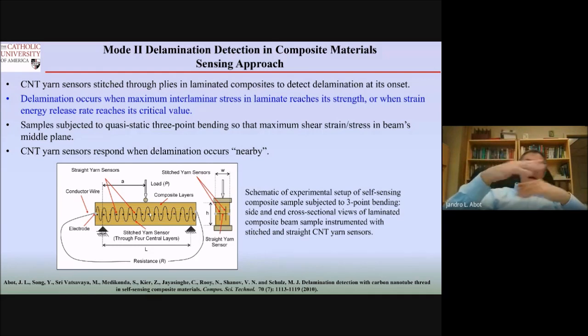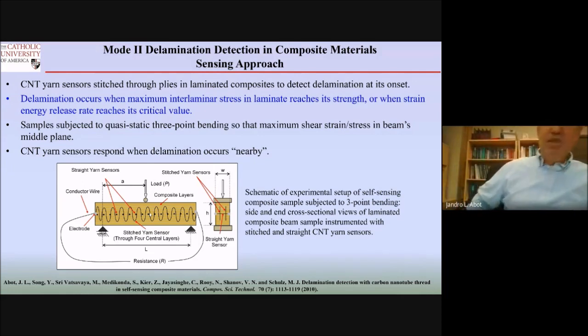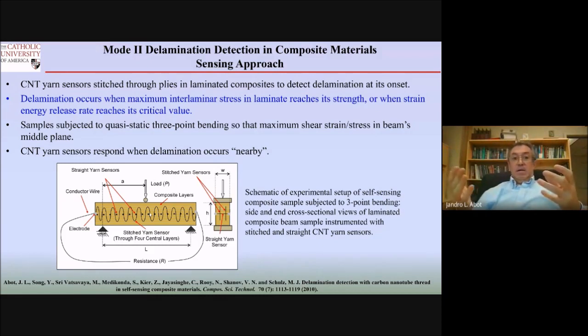Now if you keep on pulling, if the laminate keeps on delaminating, the layers keep on separating, you are pulling the fiber more. Eventually you break the fiber. When you break the fiber, the circuit is gone. You open-circuit the structure, and the resistance goes to infinity. So then I know that there is damage in the structure, and then we can detect damage.